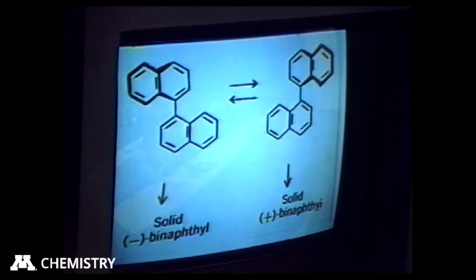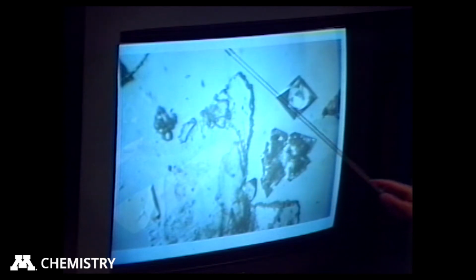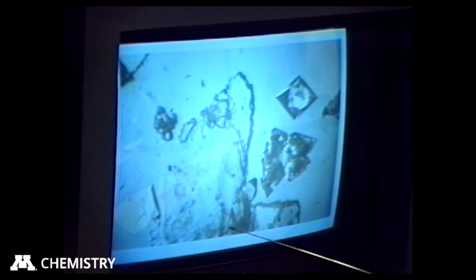But in the solid state, the most stable crystal form of this compound is a racemic form. So if you have both of these in solution and you grow crystals, you'll get these lovely diamond-shaped crystals of racemate. And what I have shown here is I had originally an enormous diamond-shaped crystal that filled this whole slide of the racemate. And that's what this is. This is the racemate here. And as we heat the racemate crystal up, it vaporizes and then recrystallizes on the slide to give these pretty little rhombohedra. And these have spontaneously resolved the binaphthyl.